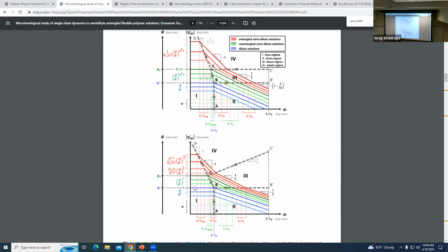It's like concentration to the power A gives you the viscosity at low frequency, for a long time. Right. So this is the normal Mark-Houwink behavior here, but as you have entanglement, you get this transition to where you see reptation, where you see the chains moving within the entanglement tubes. And then if you go to higher frequency or shorter times, then you see within the tube that you have Rouse behavior, meaning that the chains act as if they're independent chains that have this 1/2 dependence, which we'll get to later where that comes from.